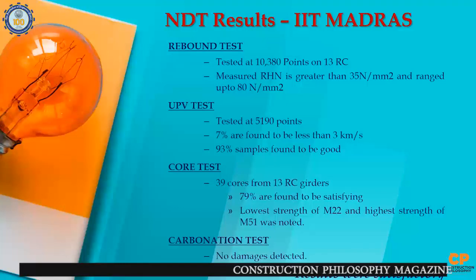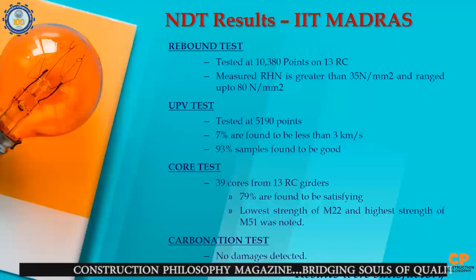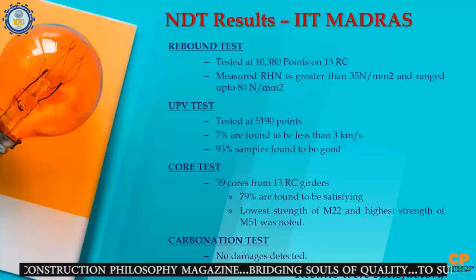And if we do a crack mapping, the 7% are found to be in the area where the cracks are already there. And the core tests were conducted, and with core tests, like I told you before, you have to be very careful, because proper sample retrieval is an issue, and then proper covering and curing has to be done, proper testing has to be made, then only the core will represent the site condition. So 79% were found to be satisfying, and a lowest strength of M22 and a highest strength of M51 was noted. And in the carbonation test which was conducted, no damages were detected. So here you can see the photographs again.